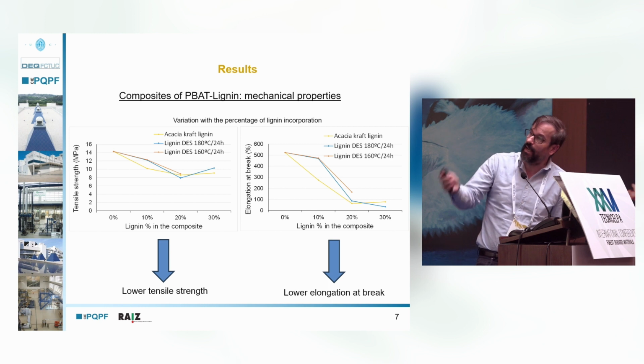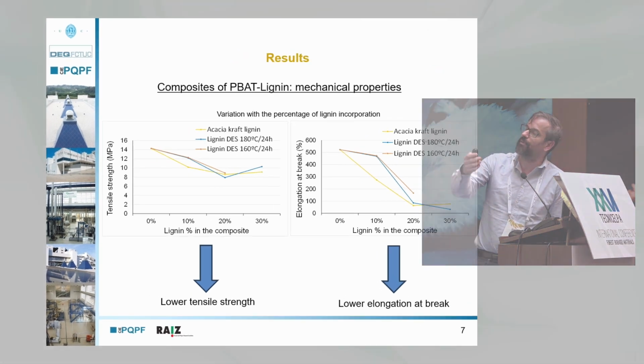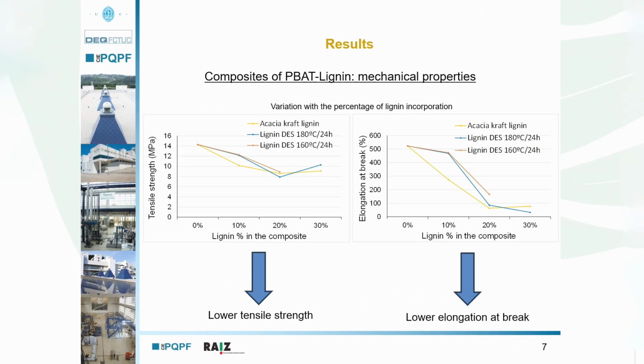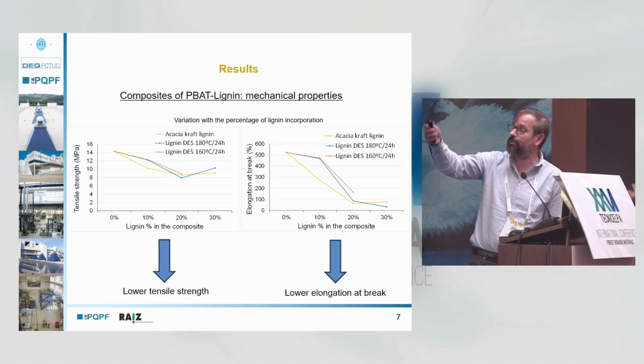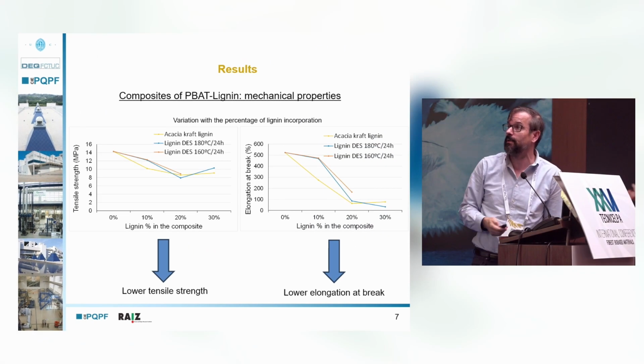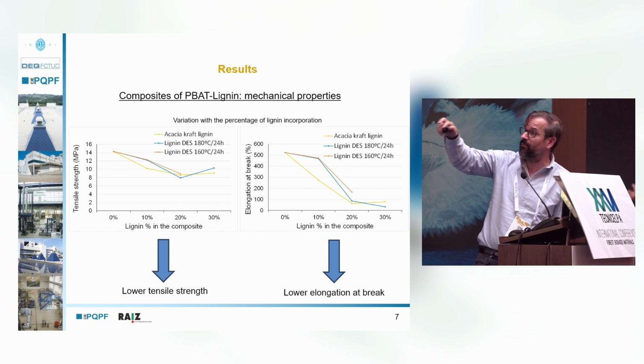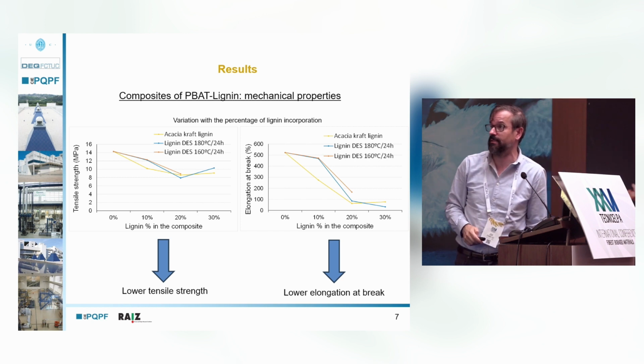You can see in the figure on the left that the tensile strength decreases, not very much, but it decreases, and then from 20 to 30% it almost reaches a plateau, and sometimes it can even show a slight increase. As for the elongation at break, it is reduced up to 20%, and from 20 to 30% is almost the same.